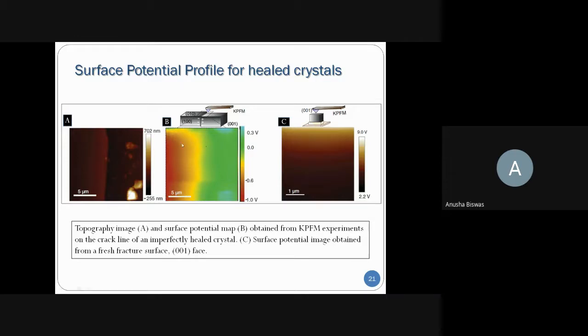Now, in panel B, this is an imperfectly healed crystal, and there also a small amount of potential is found across the crack line, which is shown here. And this profile A is a topographic image of an imperfectly healed crystal. But for the neatly healed crystal, it doesn't show any potential across the healed crack line.